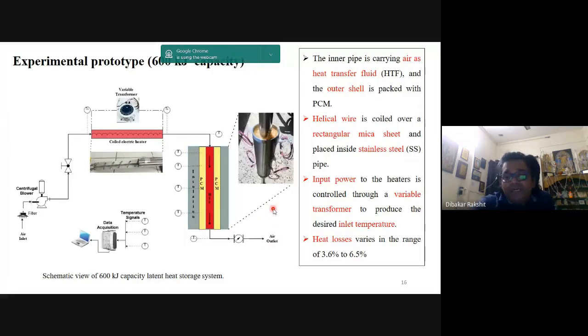Of course, we also estimated the heat loss which is happening, because if we are trying to estimate the turnaround efficiency or the efficacy of that particular thermal battery, we have to quantify how much heat loss is happening. So that also we quantified, and we found that it was within the range of say 3.6% to 6.5%.